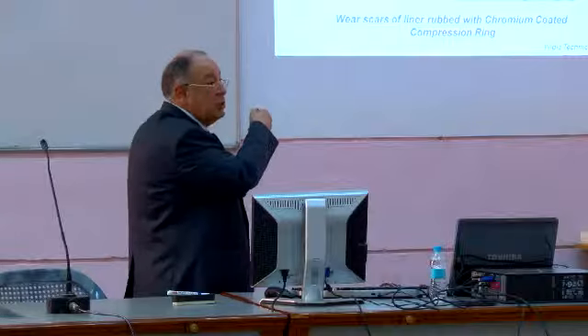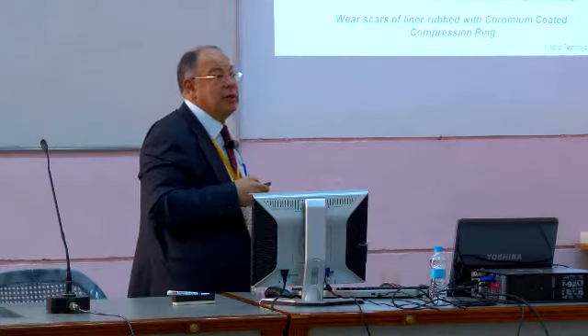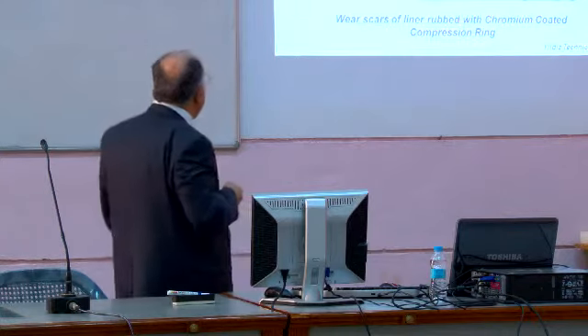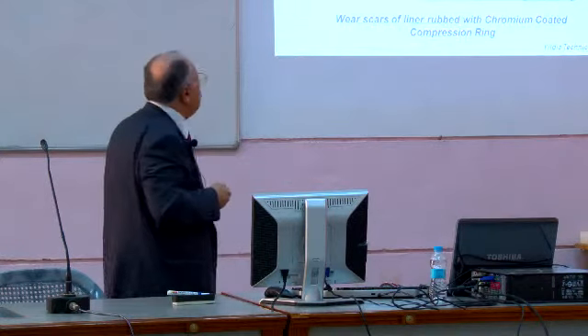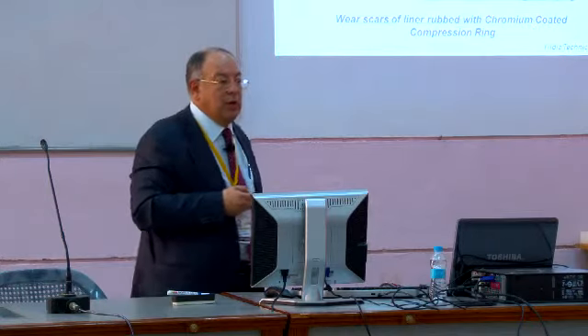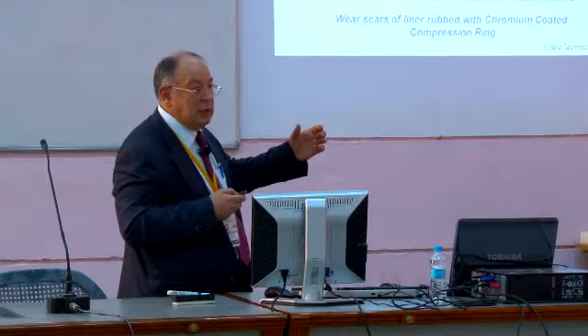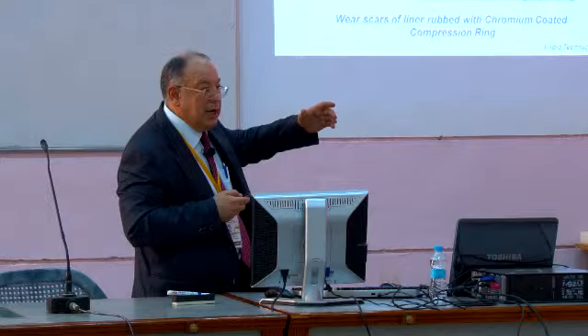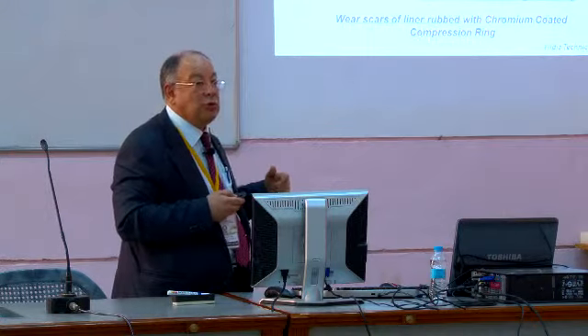This result was just obtained a few weeks ago, before coming here. This is the chromium coated test, carried out with the liner by chromium coated piston ring.